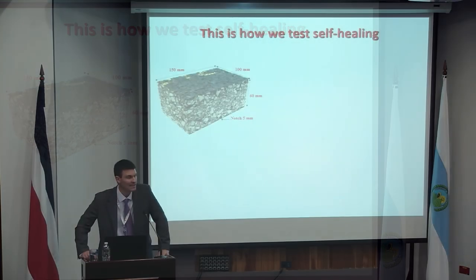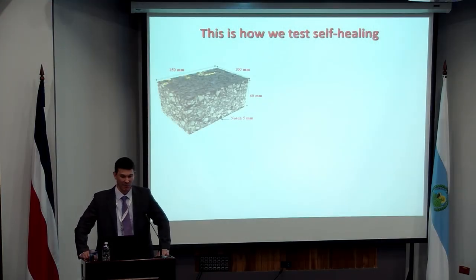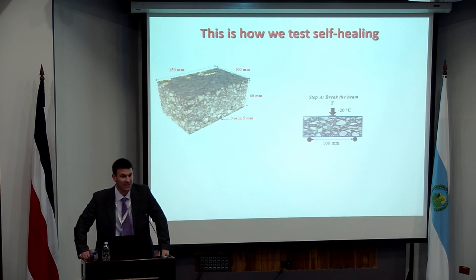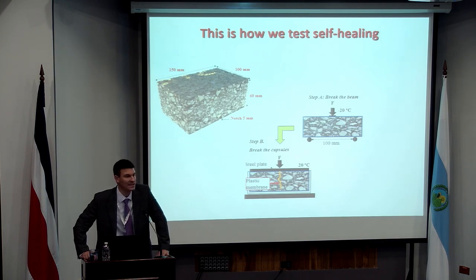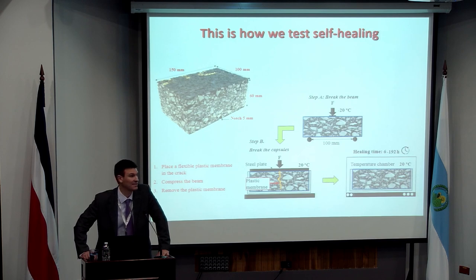So how does it work? Exactly the same way as what we did with the induction heating thing. We have a particular specimen. We subject it to some form of loading to fracture it or to damage it or to break it. We then place some form of a membrane. This is important because obviously healing will occur almost instantaneously. We want to separate that healing effect until we're ready to test. So we put a membrane between the two individual pieces of asphalt. We place it into a pressure container where we can apply load, which will activate those capsules. We take the membrane away, and then we retest.